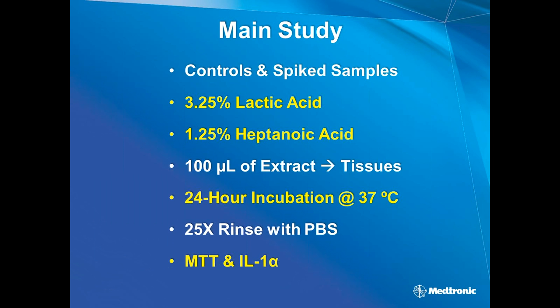So this main study, that was our range finding study, and then this main study that we did, we used slightly higher levels. If you remember, the EC50 number, I think, was about 2.8 or 2.9% for lactic acid, so we boosted that up a little bit to make sure we had enough to kill 50%. And then heptanoic acid, I think the EC50 was around 0.9%. So also we boosted this one up a little bit to make sure that if it was going to work, that it would kill at least half the cells. And we used, as I mentioned, 100 microliters placed on the apical surface of those tissues.